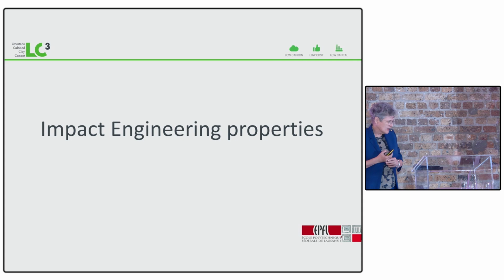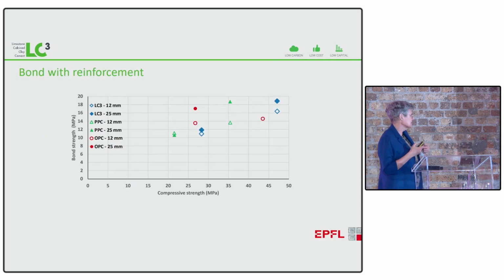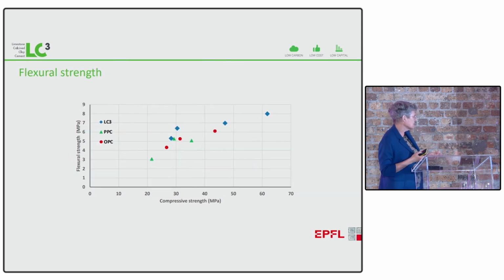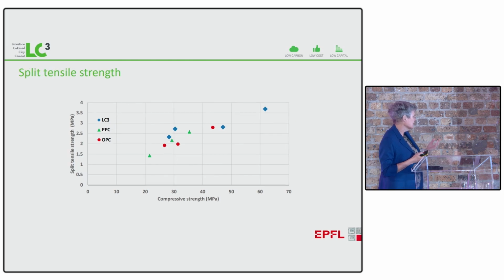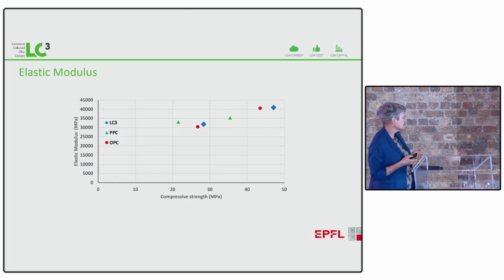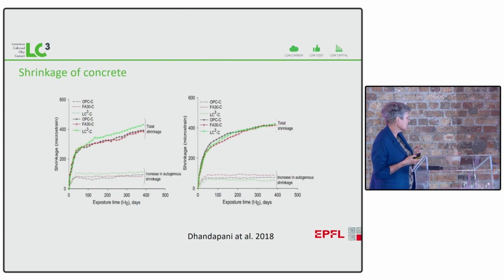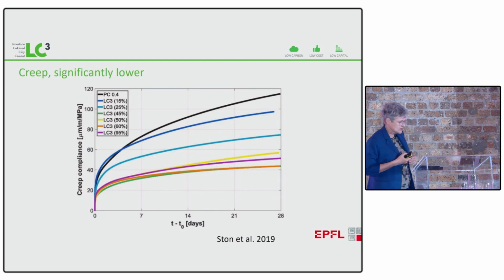And now we've studied engineering properties, and we see that these all correlate with compressive strength in exactly the same way. So here's the bond strength for reinforcement, here's the flexural strength, here's the split tensile strength. You see that all the points are on the same line with OPC and the fly ash blends. Elastic modulus, same thing. Shrinkage, all very much of a muchness. The only thing that seems to be different is the creep. And we seem to have a lot lower creep with the LC3 than we do with the other blends.